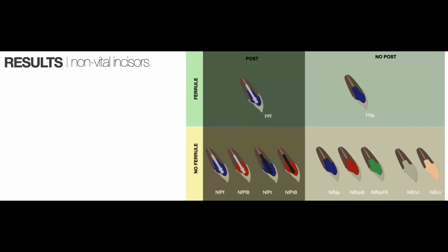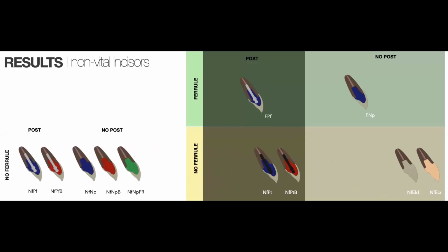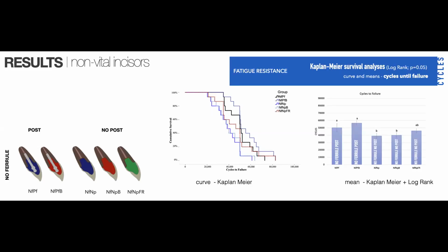When you compare the post and no post groups without ferrule, what we saw on those Kaplan-Meier curves is that everything is messed up. Everything is close to each other, so we don't have much difference, okay? But if you look at the graph on the right, we have those two first groups, which are A, you see little A's. Those two were better than the other ones, and those two were the groups with post.